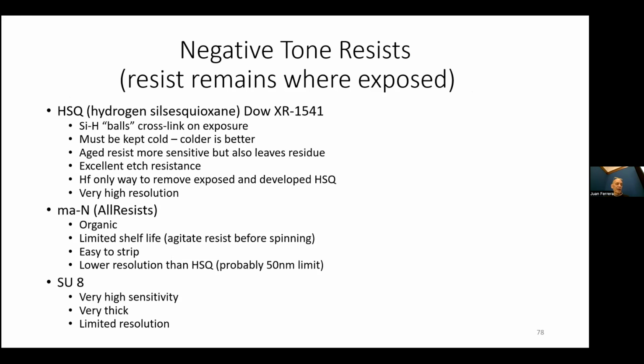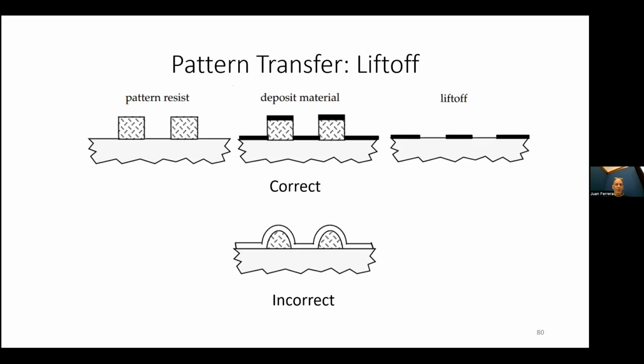There are negative resists like HSQ and MAN. Those are the only two that are really reasonable to work with. SU8 is so high sensitivity, it's very hard to work with. HSQ is wonderful, beautifully high resolution, probably the highest resolution resist, but it turns into silicon oxide, so you have to strip with hydrofluoric. MAN, on the other hand, you can strip with organic solvents, but it's a little harder to work with, and its resolution is probably around 50 nanometers, and that's if you're doing a really good job.